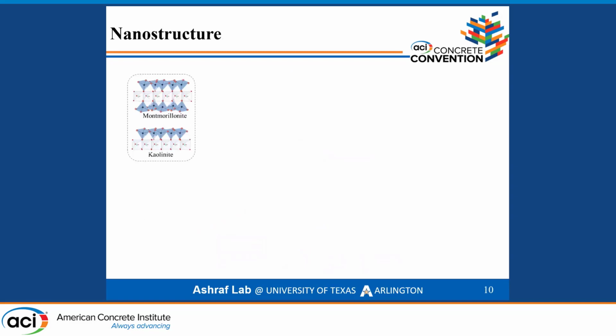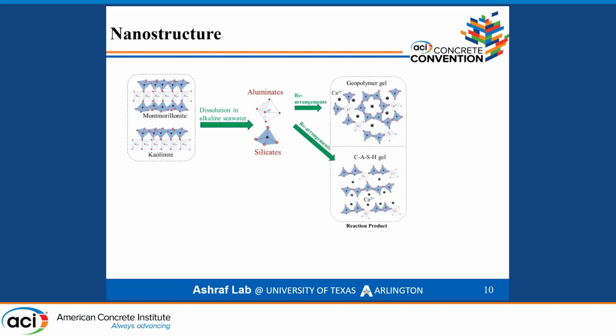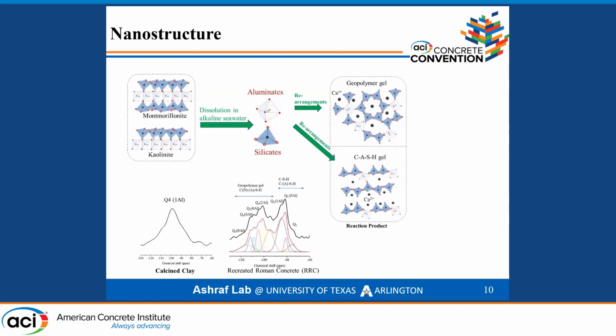As I previously mentioned, we took two types of clay, kaolinite and montmorillonite. Kaolinite is a 1:1 layered structure clay where we have one octahedral alumina sheet connected with one tetrahedral silica sheet, and montmorillonite clay is a 2:1 layered clay where we have one octahedral alumina sheet connected with two tetrahedral silica sheets. When this clay comes in contact with the alkaline seawater, the aluminates and silicates from this clay get dissolved. And when it reaches the saturation limit, these aluminates and silicates get precipitated and rearrange between themselves and form some reaction product. We used silicon NMR to characterize these products.